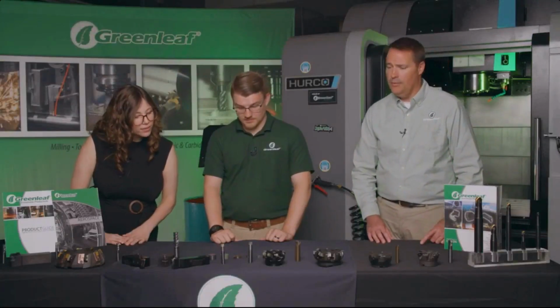A lot of our ceramic grades can be utilized for cast iron turning and milling applications. The primary ceramic grades for maximum productivity are our GSN 100 and Xsytin-1. The GSN 100 is a hot press silicon nitride grade, which offers outstanding tool life in cast iron machining at speeds up to 5,000 surface feet. This grade works exceptionally well in multiple cast iron applications and may be one to look at if you're looking to maximize productivity for your cast iron machining application.